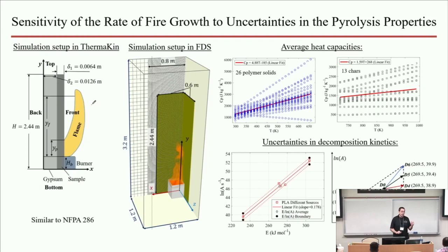But the main reason why we're so sensitive to heat capacity is because it is a difficult measurement to do well. It's experimentally difficult to obtain a measurement of the heat capacity within an uncertainty of about 10% or less. It's even more difficult to get this data well at elevated temperatures.